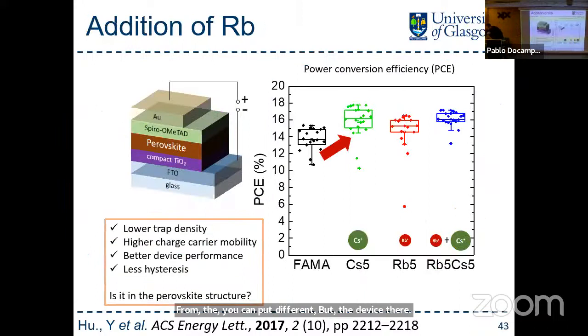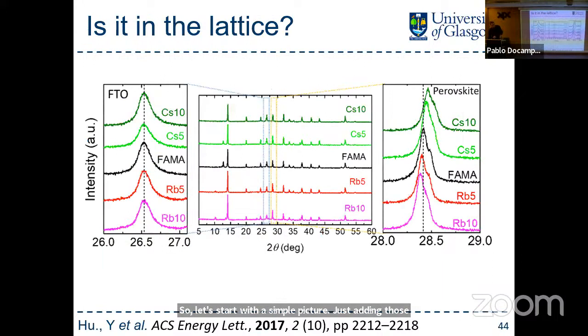Why? So we looked at that a little bit. We saw that when we added a bit of cesium and a bit of rubidium, our devices did get better. So we started with a simple mixture, just adding those two, to see if we can identify what is going on. The first thing we normally do is check: have we made the thing that we think we've made? Rubidium is smaller than cesium, and is smaller than formamidinium and methylammonium. So you'd expect the lattice to contract if it goes into the lattice. Same with cesium. Cesium is smaller than methylammonium and formamidinium, so it should make the lattice smaller. And indeed, when you look at cesium, you see that your perovskite peak shifts to the right, and that just means the lattice is smaller.